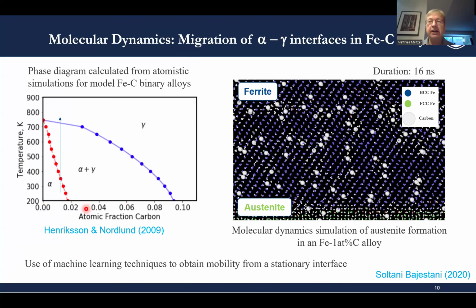Okay, 0 Kelvin, nothing moves. If we want to have a moving boundary, we have to move on to maybe molecular dynamics as a technique that can be used. And with molecular dynamics, there are a number of challenges. Challenge number one is we have empirical potentials that may not exactly describe the material that we are interested in. The other challenge is we are on the time scale of atomic vibrations. So the simulation that we can do is in the order of nanoseconds in terms of microstructure evolution, so tens, hundreds of nanoseconds.